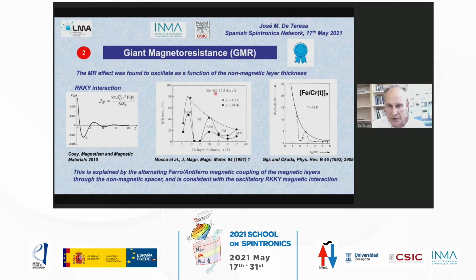Yes. So we see here one example with cobalt copper multilayers. It was found when this magnetoresistance was tried to be measured that for certain copper layer thicknesses, they did not observe any magnetoresistance. It's because they could not achieve this antiparallel configuration between the ferromagnetic layers. But in other copper layer thicknesses, they were able to observe a large magnetoresistance because there was an antiferromagnetic coupling between the ferromagnetic layers due to this RKKY interaction. So they were at the right distance to observe this antiparallel configuration. Similarly, it was found in the iron chromium multilayers.